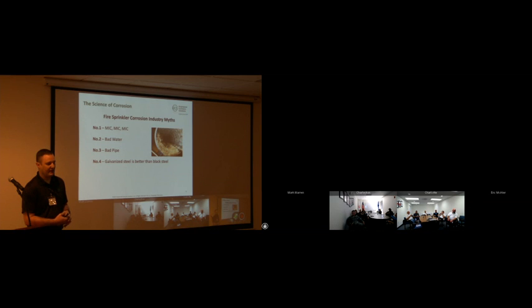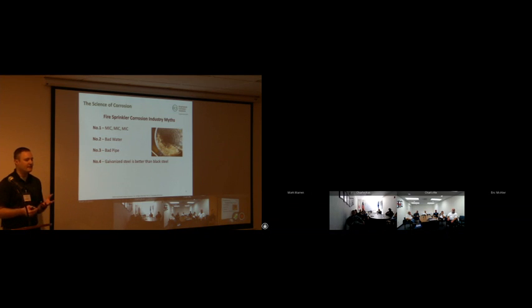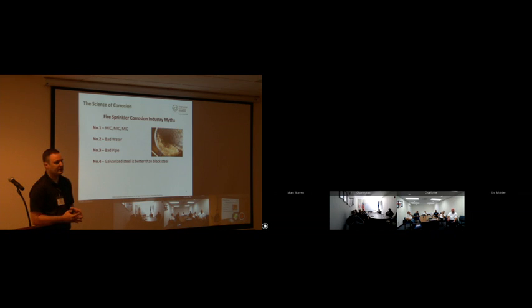The galvanized pipe was thought to be a good solution because when you galvanize a piece of metal, what that means is you take a base metal, substrate metal, like steel, you put a layer of zinc over it. That zinc will then oxidize and it forms what we call the galvanization layer, that dull gray looking color that's a zinc oxide. And what it does is it prevents oxygen from getting down to the steel. So what the industry found out, well, actually the auto industry did a bunch of research on this in the 80s. And what they found out was in a persistently moist environment, that zinc layer will actually convert to zinc hydroxide, and it will actually come off the base metal. So then you get little areas in the base metal that are exposed and that they will corrode preferentially.